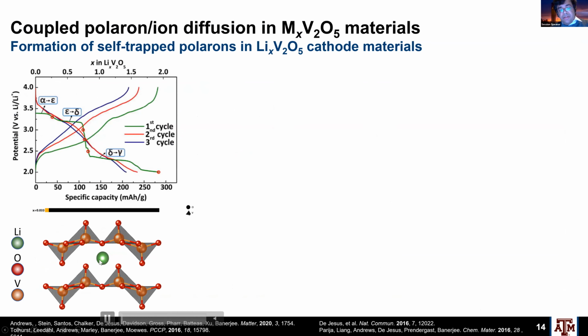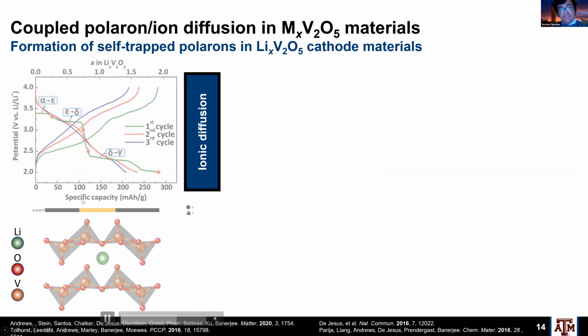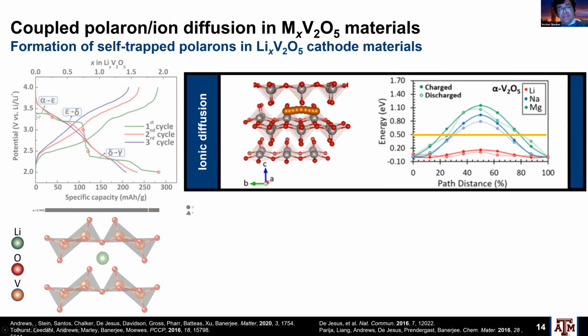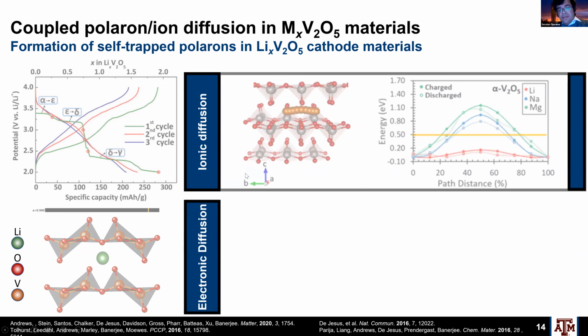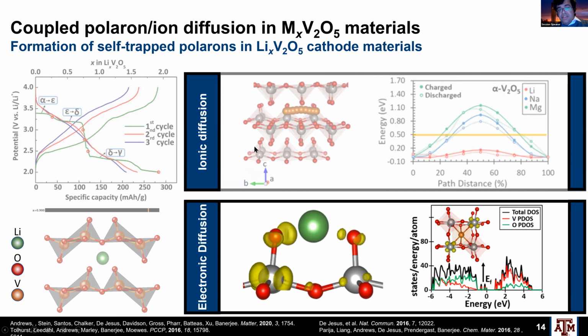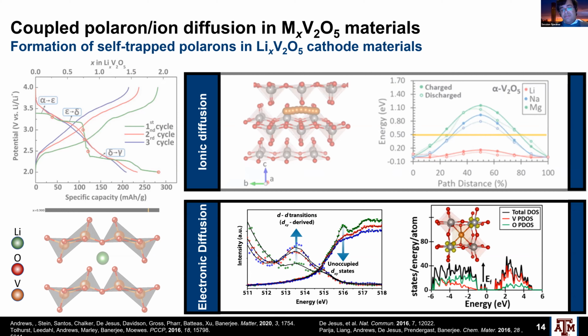So, okay, if I were to look at the electrochemistry here, you can see the structure change as a function of the lithium ion concentration, okay, and the layers pucker and get more and more distorted and start pulling apart, okay. And in terms of the electrochemistry, you see distinctive plateaus corresponding to alpha to epsilon, epsilon to delta, delta to gamma, and so on and so forth, okay. And again, these summarize the challenges between ionic diffusion, electronic diffusion, and really, perhaps most importantly, the coupling of these two phenomena as a result of small polaron formation.